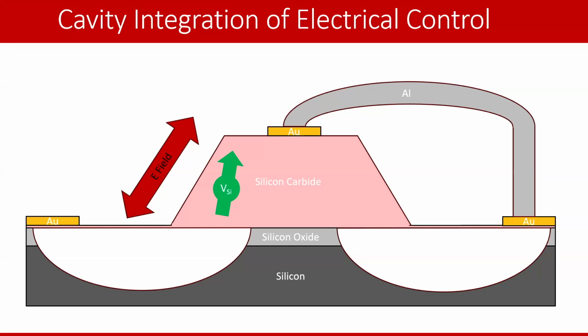And this is a silicon carbide chip on top of silicon oxide, a thin layer of silicon oxide. This is about 400 nanometers. This is actually to scale, this PowerPoint drawing, on top of silicon. And so if we want to make this whispering gallery mode resonator that you saw before, this kind of suspended membrane, then we want the optical mode to travel around this way. We need to be undercut so that the silicon doesn't destroy the optical mode.